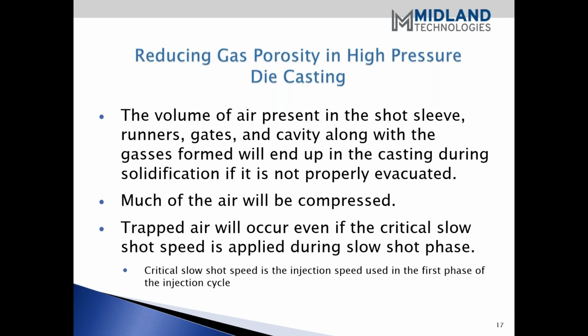As a rule, if you use PQ square and you do some calculations to determine the critical slow shot speed, you'll determine pretty quick that most machines, in particular the older machines, are not capable of achieving the recommended critical slow shot speed, which was intended, when the calculations were developed in the industry, to minimize the amount of air. It's extremely difficult. If you have a die casting machine with a parabolic shot end, you can help yourself somewhat to evacuate and help create a less turbulent condition, with less mixing of the air with the molten metal. But it is very difficult to achieve critical slow shot speed.